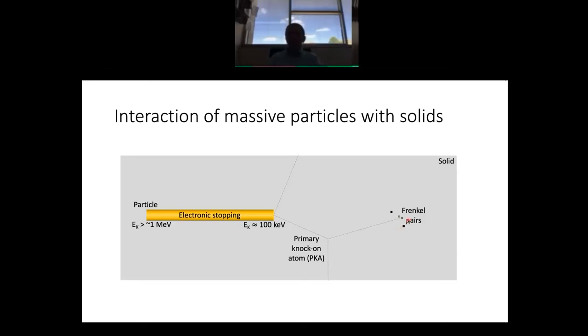That damage occurs in the case of crystals in the form of Frenkel pairs, so vacancy interstitial pairs. These open circles that I'm showing you here are vacancies. The squares are interstitials. So a vacancy is a missing atom, an atom that should be at a certain lattice site and is missing. And the interstitial is an extra atom that's been squeezed in between other atoms, right? So the thermal spike will generate these Frenkel pairs.